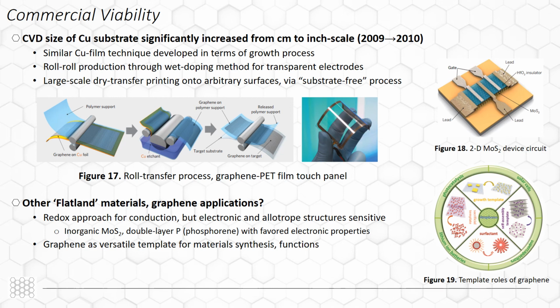This method was applied through fabrication of low sheet resistance and high transparency doped 4-layer transparent electrodes, which were therefore superior to commercial ones of indium tin oxide material. High-strain functional touchscreen panel devices were also produced using this process.